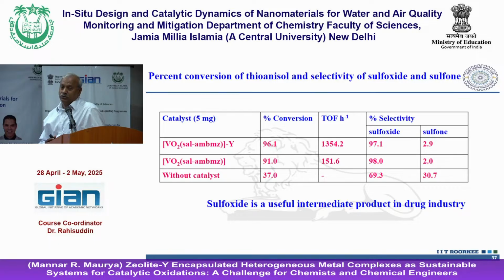but if the desired one is only sulfoxide, in some cases it is giving some percentage of sulfone. When you do it without any catalyst in the presence of oxidant, you will see that the result is very different. It means our catalysts are becoming more selective towards the sulfoxide, not the sulfone. So we are getting a good amount of at least sulfoxide.